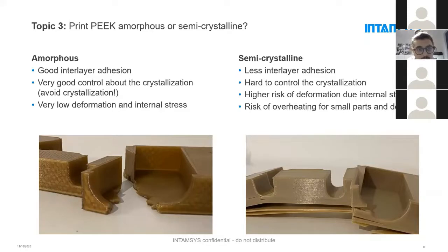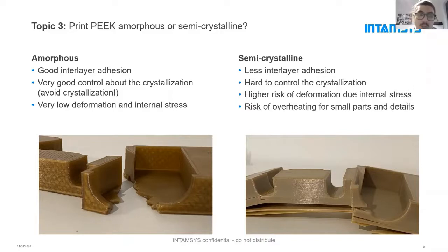One question that is definitely one of the most asked questions is, do I print amorphous or do I print semi-crystalline? PEEK itself is a semi-crystalline polymer, which is very tough to print, which is mostly related to the semi-crystalline structure. PEEK has a very sharp crystallization point. So when you start to melt it, you break up the crystallized structures, and when it cools down, it crystallizes again. The problem that you have with semi-crystalline parts is that it's very hard to define when they crystallize or to have an influence on when they crystallize. And this is the trick within amorphous printing.